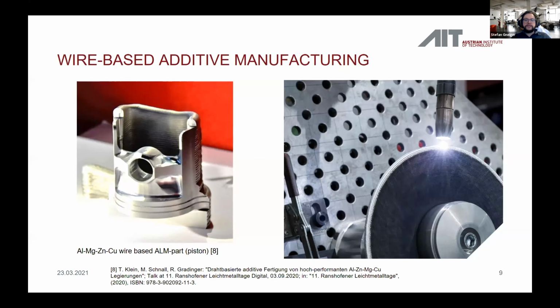Here you can see 2 examples of parts produced with the wire arc additive manufacturing. On the left-hand side, it's an aluminum part, but I use this to show you one side is the milled surface where you have already the finished part. And on the back side, this is still the as-fabricated state, how you receive it from the wire arc additive manufacturing process. You can also see that the surface quality is quite good. And here you have additional material which has to be milled away for the final geometry. And on the right-hand side, you can see an example of a rotary part. The diameter of this is about 30 centimeters.